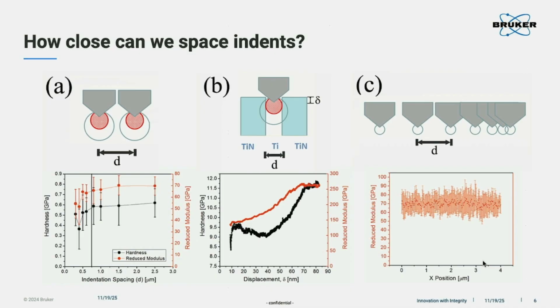For example, if we look at this, we want to make sure all the plastic deformation is not overlapping. This is very important because if you are very close, you will see that all the indentation marks mix together. The data cannot be accurate. So if we look at this example, you see this is the indentation spacing. Once you get the indentation very close, the data becomes messy and uncertain. Once you separate enough, the data becomes stable. This is the one thing we need to define before we process the properties mapping. Okay?